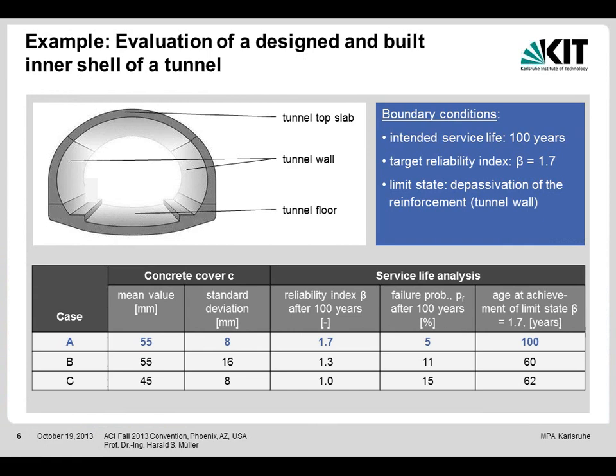Then we arrive at the age of life of 100 years. For example, if there is bad execution and we have a mean concrete cover of 55, but a standard deviation of 16 millimeter, you see that the age at the achievement of the limit state reduces to 60 years. This is a tremendous difference. 40 years earlier, there are much more damages.